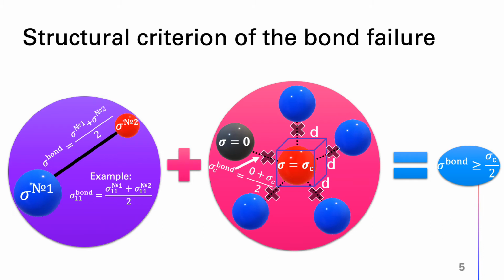The failure of a structural block is interpreted as the failure of all bonds of the peridynamic particle occupying a volume in the form of a cube with an edge of size d. If we consider the case when a critical stress is reached in the considered peridynamic particle and its neighboring particle has even a zero stress value, then the connection between them has to fail. Therefore, we obtain that the critical bond stress is equal to a half of the quasi-static strength of material sigma c.